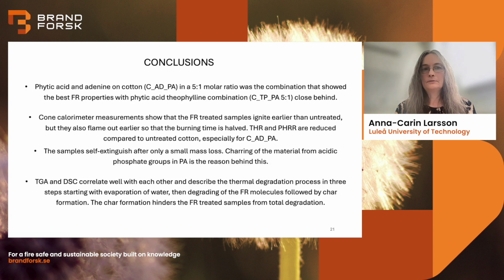The char formation caused the samples to self-extinguish after only a small mass loss, and it's the phosphate groups in PA that are known to cause this charring.